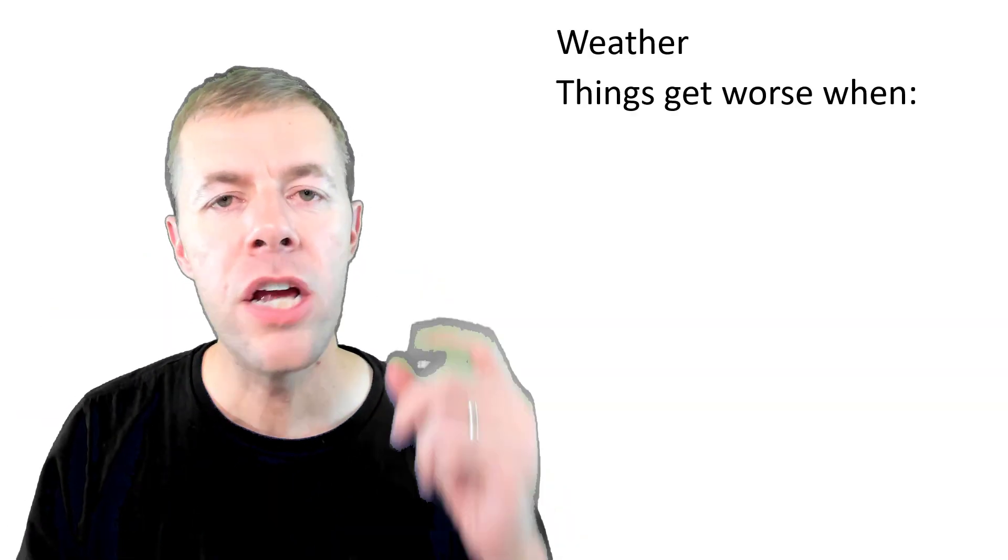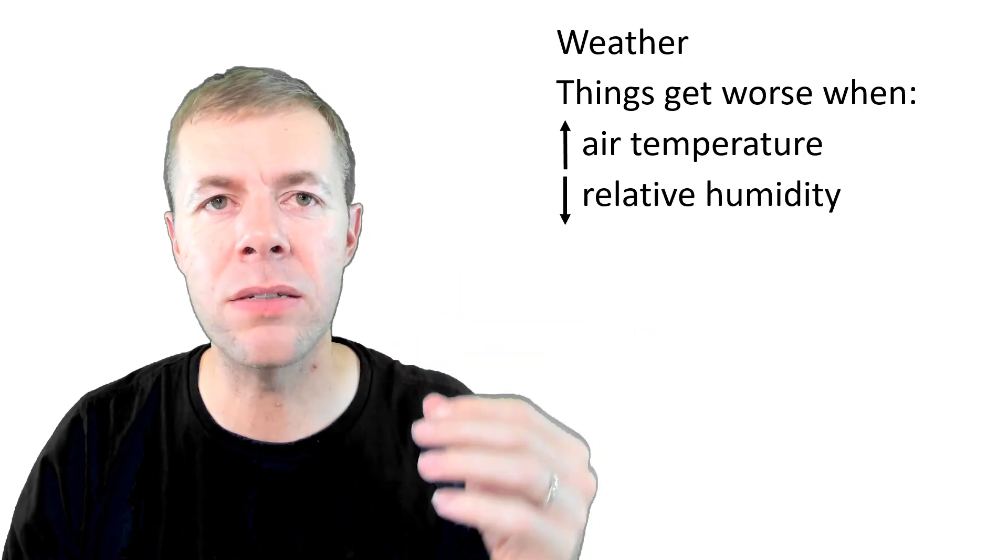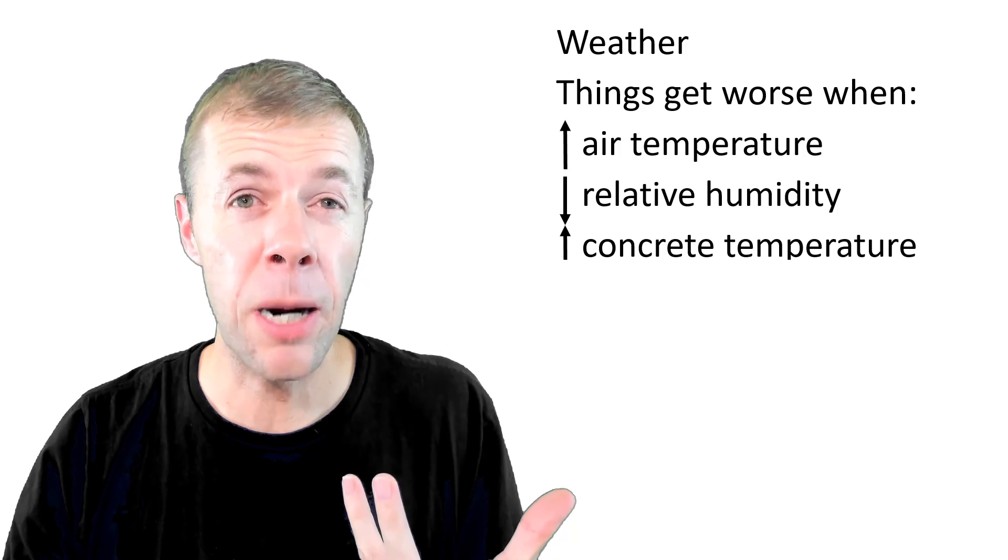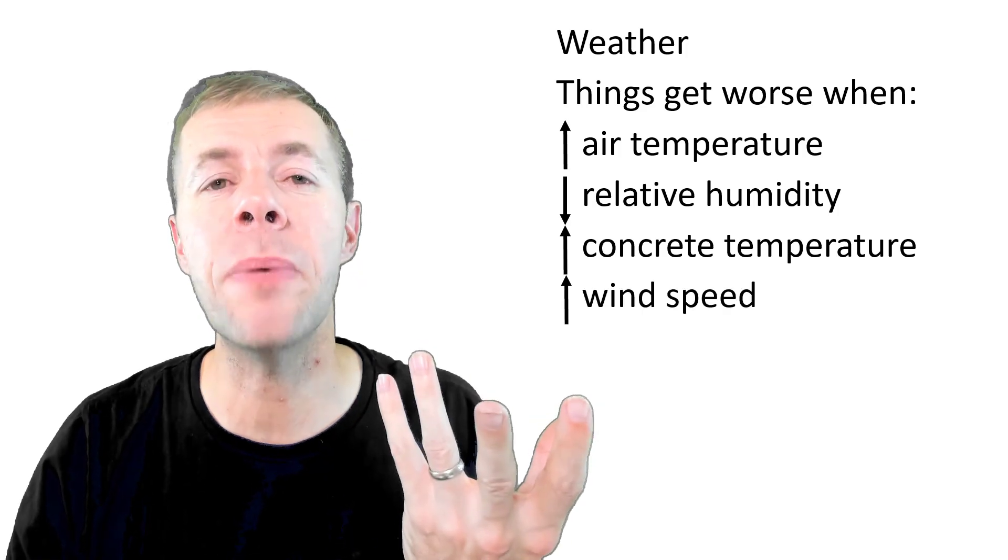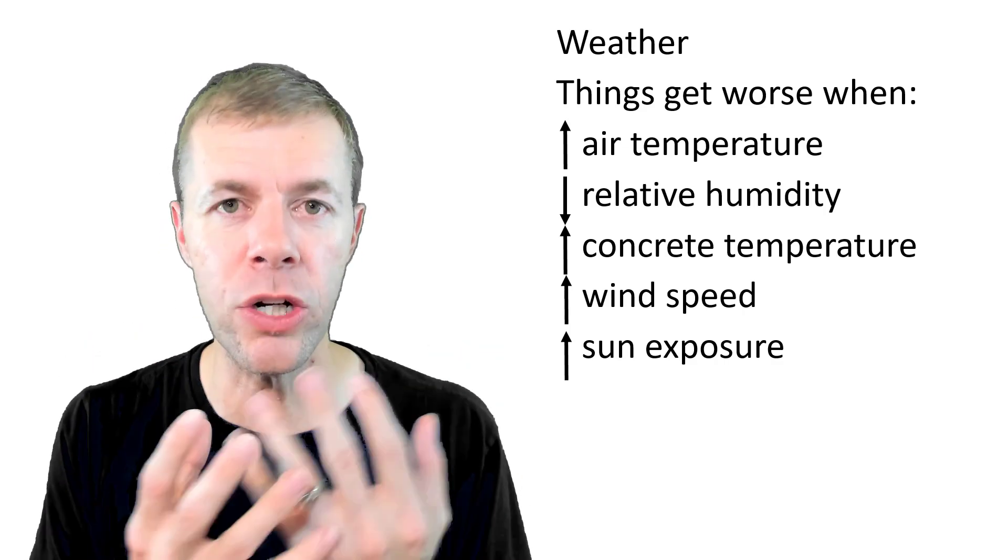But it's not just about the concrete, it's also about the weather. Things will get worse when your air temperature is higher, when your relative humidity is lower, when your concrete temperature is higher, when the wind speed is higher and sun exposure. Think about the things you worry about when you get chapped lips or a sunburn. That is the exact same thing you have to worry about with your concrete in this plastic shrinkage cracking.